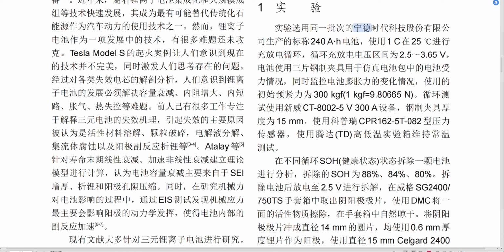So what they use for the study is the CATL cell. They're using the 240 amp hour cell from the same batch, and they cycled at 1C, 25 degrees C. The cycling voltage is 2.5 volt to 3.65 volt. I will highlight the major specs or major information, and you can find them later. I will share this paper in a link.